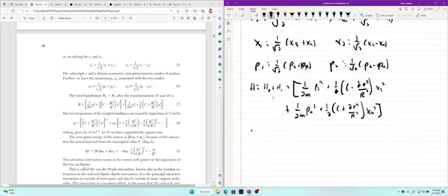So the calculated cohesive energy is when the atoms are at rest. Quantum mechanical corrections act to reduce the binding by 28, 10, 6, and 4% of equation 16 for neon, argon, krypton, xenon. So what we see, right, is quantum mechanical corrections reduce the binding a lot more for neon, and then as you get heavier and heavier, it reduces it less. So the heavier the atom, the smaller the quantum correction. Quantum, small stuff.